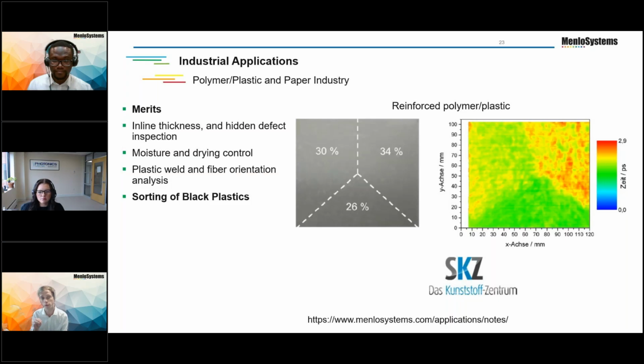So if you're looking for specific spot defects in a material, generally with terahertz, this is your spatial resolution. However, if you can find that kind of response, and as you can see here with the different degrees, we can see the different material compositions of the polymer in different segments, and you can also see that we scanned across millimeters there. However, the spatial resolution at sub-millimeter tends to get a little difficult. So depending on the defect size you're looking for inside of that material would be, I think, the biggest limiting factor. But the material properties themselves seem very well suited to terahertz.